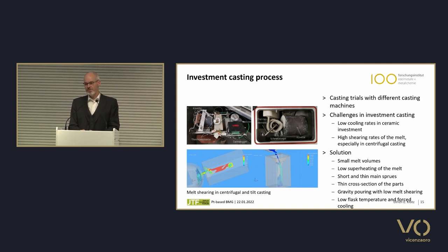and the high shearing promotes the crystallization. So therefore, we first thought, well, we want to do it in tilt casting, but in the end, it was working also in centrifugal casting in gold. This was our experience from the gold alloys. In gold, this was critical, but it's not critical for platinum alloys.